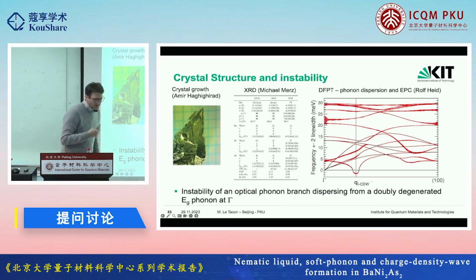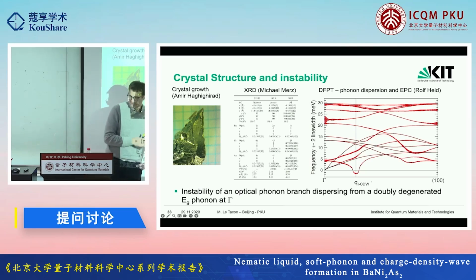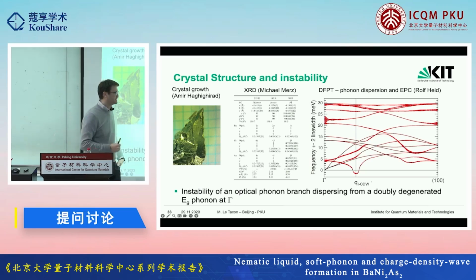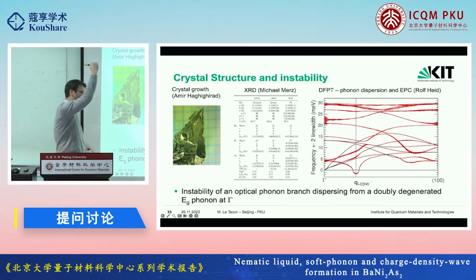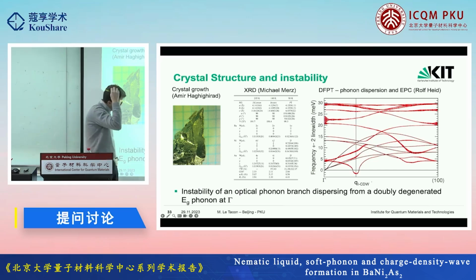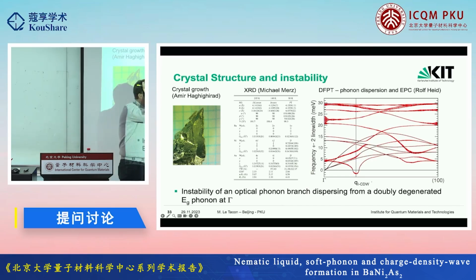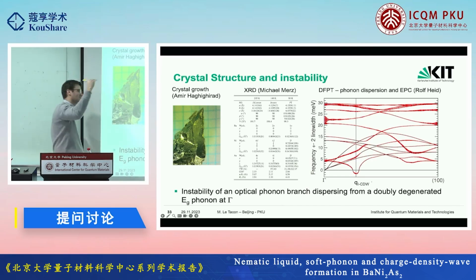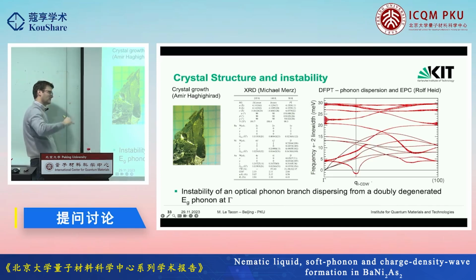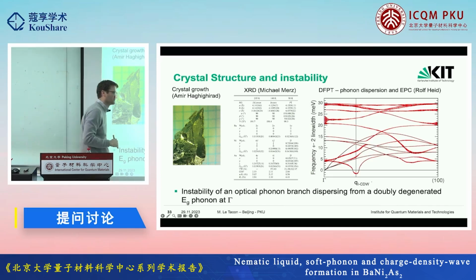And so I tried to get Rolf calculating for me the real part of the susceptibility, and he's very reluctant to that because basically it says that you really have to integrate over all your electronic bands quite deep in the dispersion. And that could give us some hints there as well, but I found a new way. Actually, I couldn't sleep this night, and I thought of it: we just make the joint density of states at different frequencies deeper in the dispersion, and then he cannot tell me no.